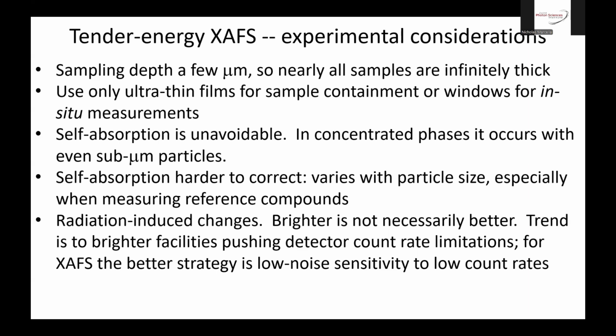Sometimes you really want to go the other way and optimize the detection of low signal and low noise measurements, because that's what you need to preserve your sample. A good example that we published recently was looking at sulfur in glass, and it was a hydrous glass. And the measurements were made at an undulator beamline at APS at medium intensity, and they saw the change go from one phase to another, from the first scan to the second scan.